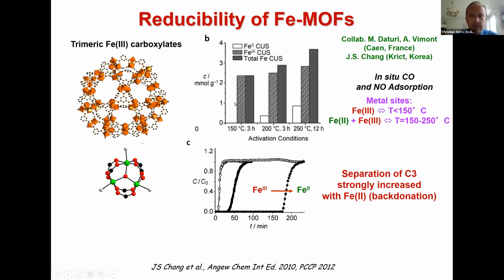So you can see here at the top the number of accessible metal sites as a function of the activation temperature. Initially, at lower temperature, you have only iron 3 Lewis acid sites. But as soon as you increase the temperature, we were very surprised to see the appearance of additional iron 2 metal sites. But the main surprise was that these sites were not due to a reduction of the iron 3 open metal sites into iron 2, but to the creation of additional metal sites. And the explanation comes here.